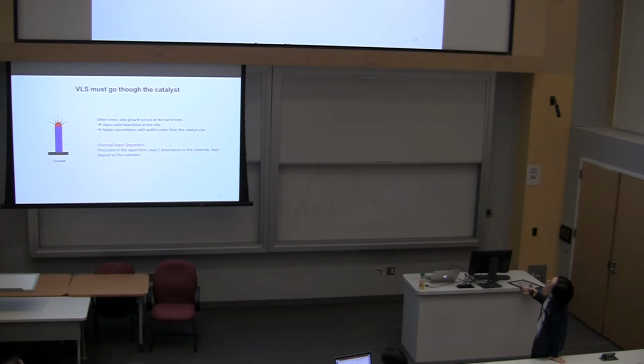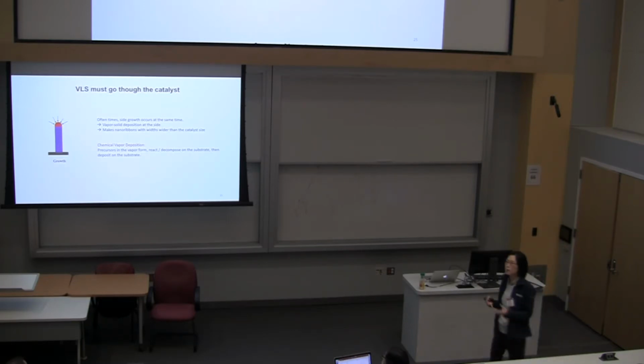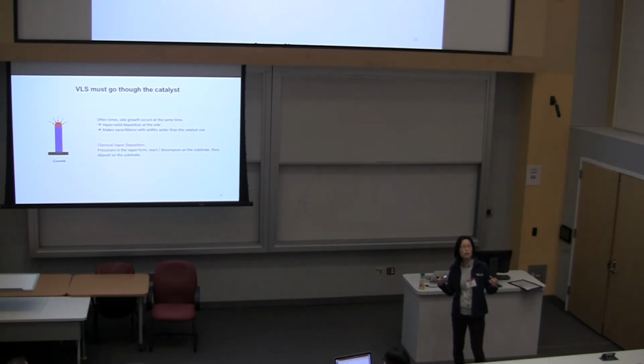For VLS growth, it must go through the metal catalyst. Strictly, VLS only goes through the metal catalyst. Oftentimes there's a side growth that happens by vapor going directly to solid, vapor-solid deposition. That's why for bismuth selenide and bismuth telluride nanoribbons, the width is generally much larger than the size of the nanoparticles, because there's a constant side growth. So if you want to be very pedantic about it, you wouldn't call that VLS growth. You would call it metal catalyzed. The metal still acted as a nucleation center to catalyze the growth, so you would call it metal catalyzed CVD, chemical vapor deposition growth.